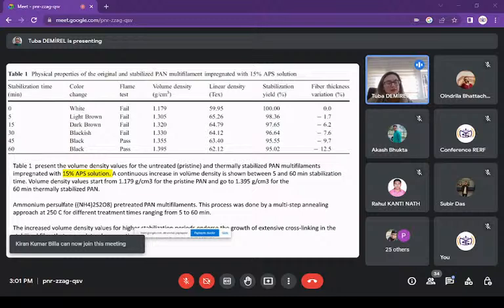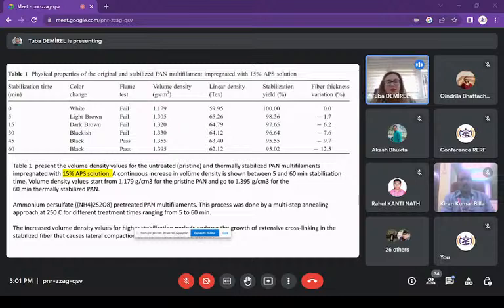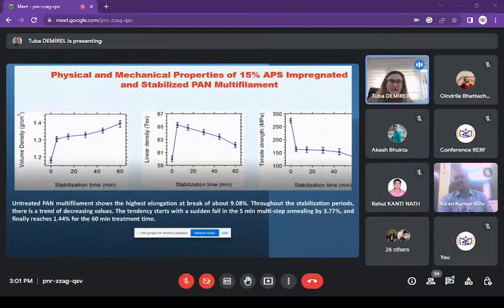Cross-linking is a ring-forming molecular structure that is important in the stabilized fiber and causes lateral compaction. This fiber's physical and mechanical properties: with 15% ammonium persulfate impregnated, the volume density will increase. Linear density increases then reduces, and tensile strength is permanently reducing.